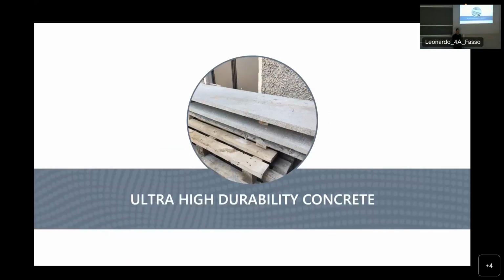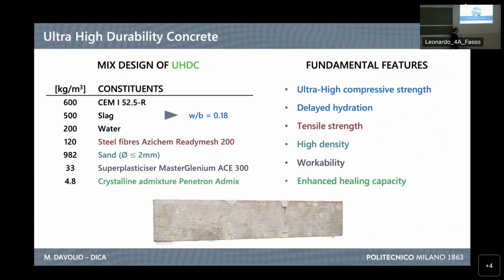And as I introduced the concept of this new material, ultra-high durability concrete, I will now briefly describe its properties. Starting from the mix design, the things I want to point out are the significantly low water-to-binder ratio, which of course guarantees a high compressive strength, and also the delayed hydration, which characterizes this material due to the unhydrated cement particles inside the matrix after casting. Then we have 1.5% by volume of steel fibers, which give this material a remarkable tensile strength. So we will see what the results of this kind of mix design are.